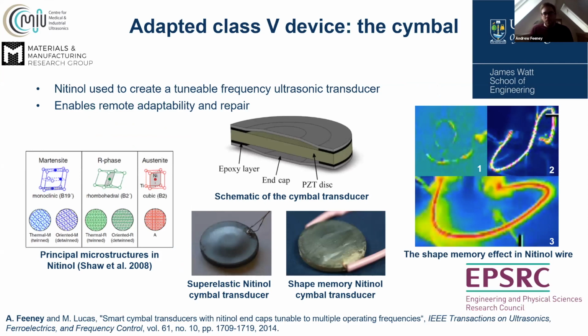Now, nitinol is an alloy of nickel and titanium, and it's a shape memory material. It exhibits two major microstructures with different physical properties and a third intermediate phase, which we call the R phase. The change in these microstructures, for example, through modest changes in temperature, and they can be very modest, in the order of only a few degrees Celsius, permits property changes in the material. One of these is elastic modulus, for example. Changing this elastic modulus causes a change in device resonance, and this is achievable in the order of thousands of hertz, which is ideal for an ultrasonic transducer if I want to make it adaptable.